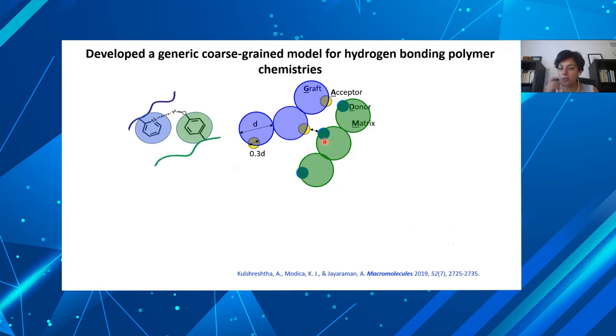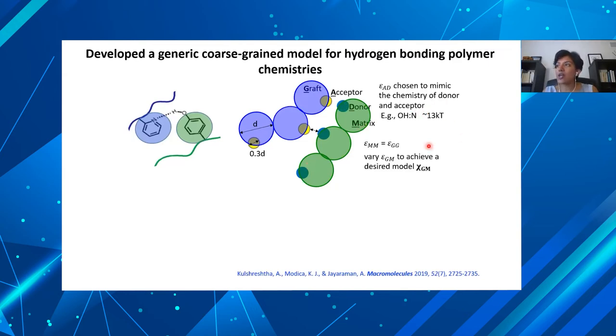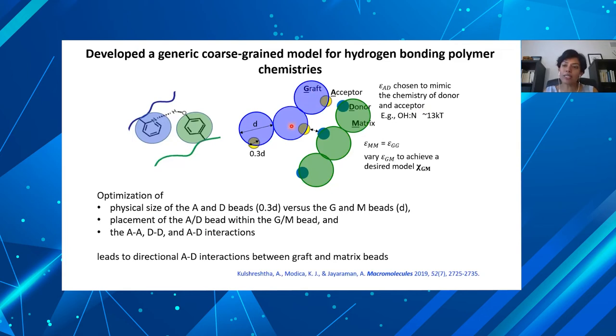This is a phenomenological coarse grain model where we are bringing about the effect of that directionality that one may see in hydrogen bonding through this coarse grain model. We do that through the choice of these light, small beads, which we call sticky beads, ghost beads, that sit mostly within the monomer beads. And that little exposure of that sticky bead is what gives that attraction, that directionality. It's a tiny volume where that attraction is felt. So the choice of attraction strength, the size of the beads, where they are placed, what bonded interactions they should have, how restricted they should be along the backbone, all of that together gives the net effect that looks like they are directionally interacting. At the same time, you still have isotropic interactions between the backbone, graft, and matrix beads. So you can also isolate the two and study fundamental deeper questions because of this model. Okay, so we are able to mimic directional interactions through this.